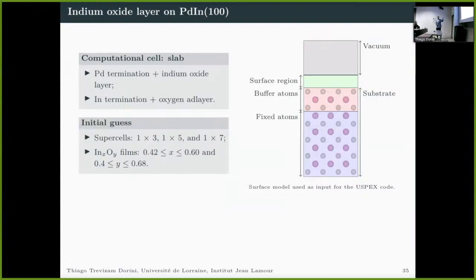So in this case, we have chosen to use 3 supercells for the substrate. Here we have a 1x3 substrate, but we also use a 1x5 and a 1x7. And we have chosen several compositions for the indium oxide system that range from about InO to In2O3.